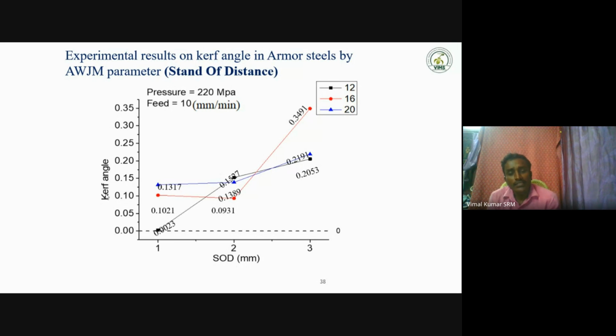If we increase the SOD, the standoff distance, on the cut surface, the water flow becomes tapered, so it is not a straight cut. So the kerf angle changes, and SOD definitely influences the kerf angle. So the kerf angle is influenced by SOD, traverse feed and pressure. The audience should understand that the kerf angle is controlled by SOD, traverse feed and pressure.